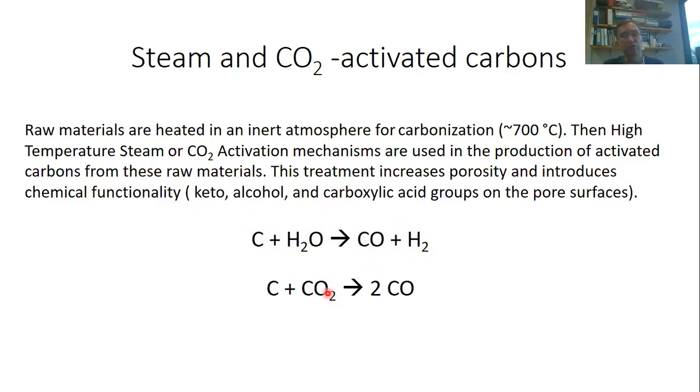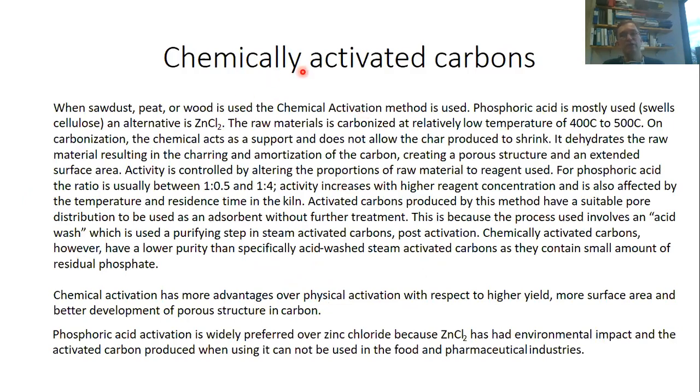When you use CO2, then you basically establish a so-called Boudouard equilibrium. So your carbon surface can react with CO2 in order to produce CO. So again, effectively, you etch away carbon from your internal carbon surface. So you increase your porosity and you increase also your surface area. So the other possibility is that you activate your carbons chemically.